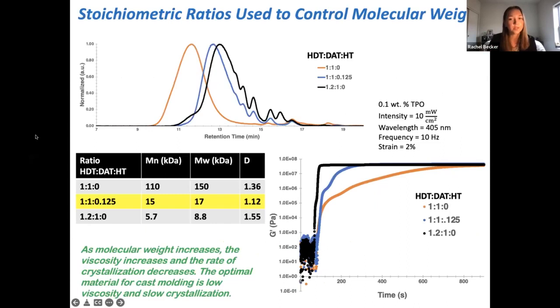So looking into the stoichiometric ratio effects on molecular weight and also crystallization kinetics, on the top left, I have GPC data of the 3 different stoichiometric ratios that we tested. And as you can see, the 1-to-1 ratio has a significantly higher molecular weight than the other 2 ratios that we tested. And this means that the 1-to-1 ratio is also going to have a very high viscosity, and high viscosity is not going to be ideal for a cast molding process, as it'll be very hard to get that melted part out of the cast. So we wanted to focus on the ratios that gave us lower molecular weights.